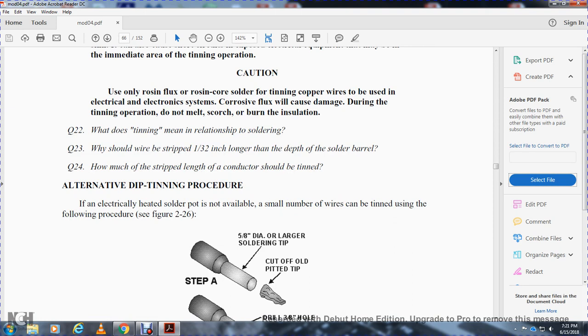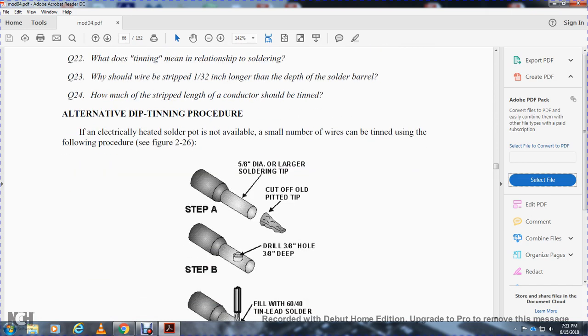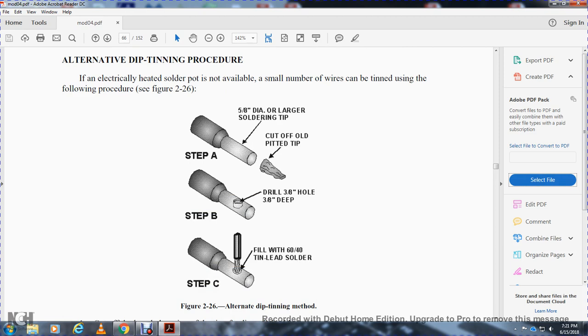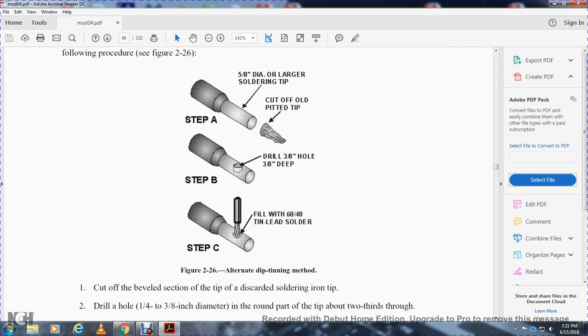Alternative dip tinning procedure. If an electrically heated solder pot is not available, a small number of wires can be tinned using the following procedure. Step A: take a 5/8 of an inch or larger soldering tip. Cut off the old tip and then drill a 3/8 of an inch hole, 3/8 of an inch deep, filled with 60/40 tin lead solder.